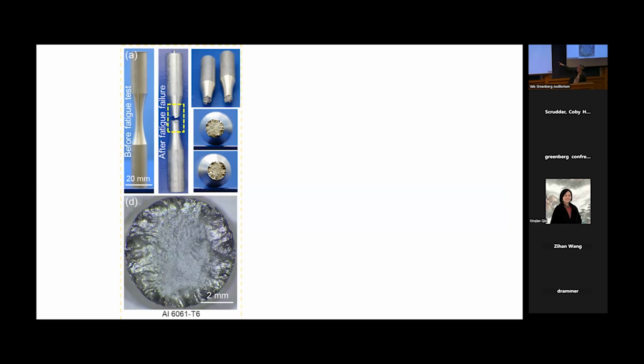And if you look at the cross section of the fracture, the failure cross section, you will see the very typical metal fatigue. The outer side, the darker and shiny part, is where the fatigue crack is propagating slowly over cycles, and then eventually the grayer section of the cross section over there is the final catastrophic breaking of the whole cross section. Okay.